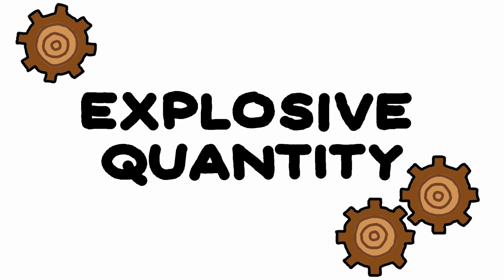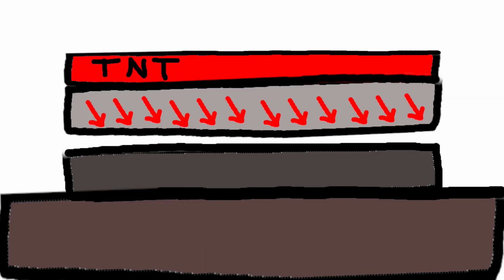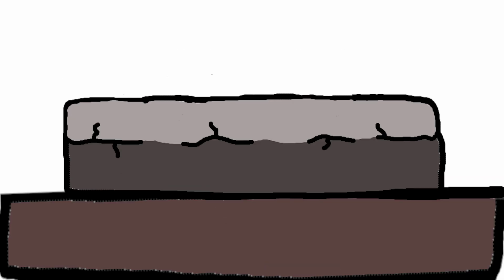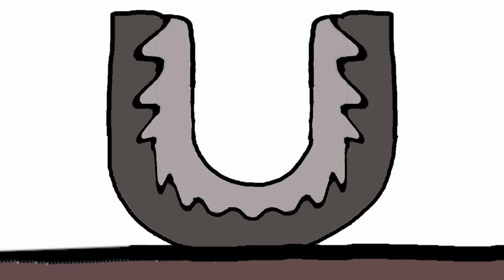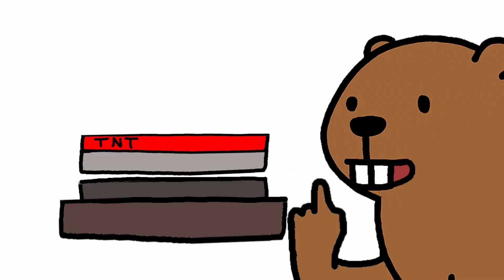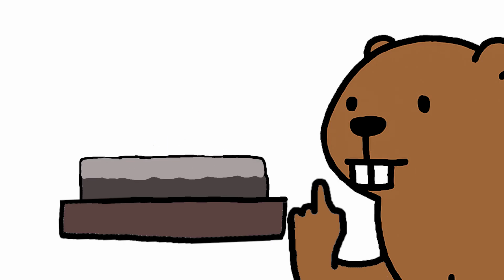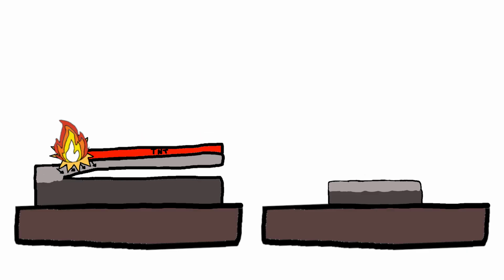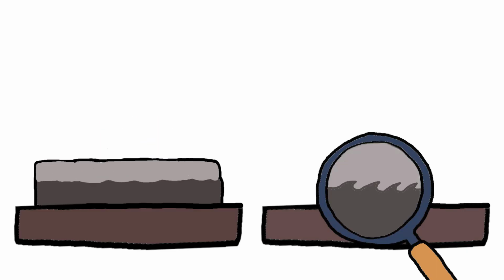Explosive quantity. The explosive quantity determines shock pressure and duration. Too little results in weak bonds and low shear strength. Too much can deform plates or produce irregular waves. Additionally, the way the explosives are set off matters. Depending on the piece size, the explosives can detonate all at once or in a wave, affecting the wave formation and interface.